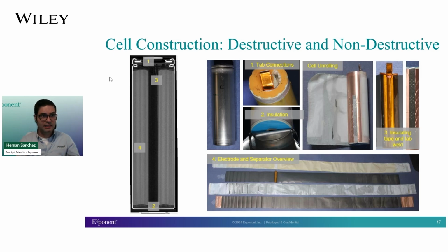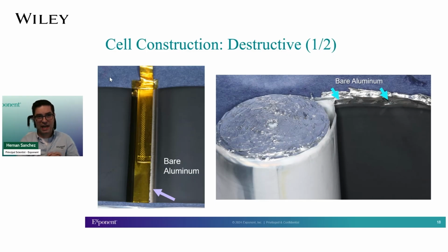And speaking of that tape, here's an example on the left of what happens when the tape is not properly aligned, and all of a sudden that leaves bare aluminum exposed. There's been a lot of research lately about what are the potential scenarios that are more likely to lead to thermal runaway, and usually having bare aluminum is one of those conditions which could lead further down the road to a thermal failure. Similarly, you could see maybe at the edge of the electrode, the one to the right, also bare aluminum. And once again, those are things that might not be as easy to detect purely from non-destructive. So it's complementary, right? You do both things.